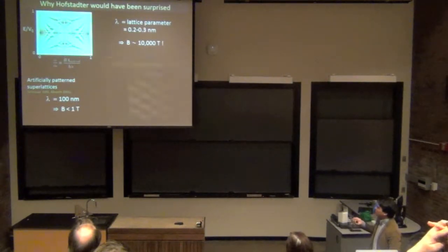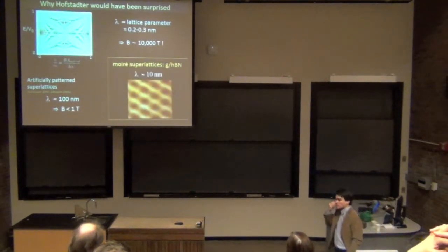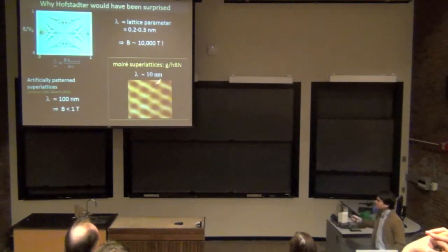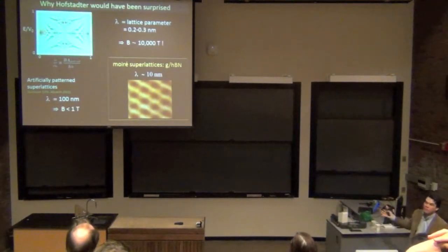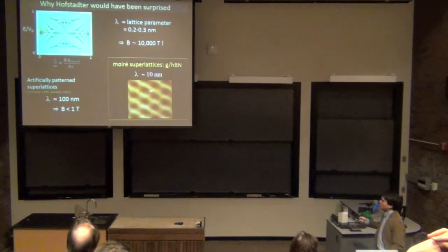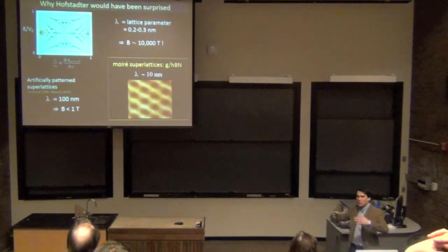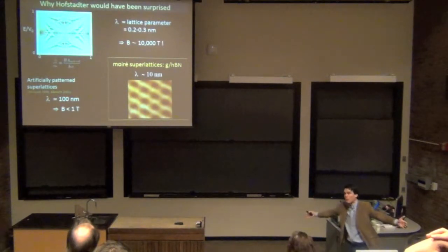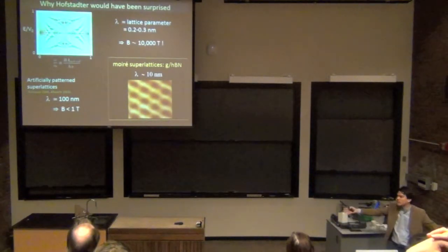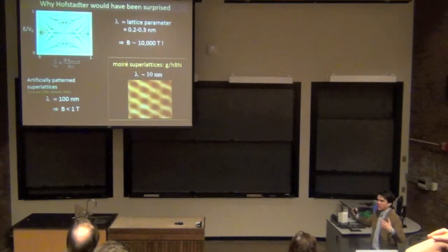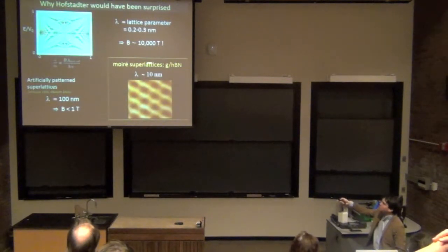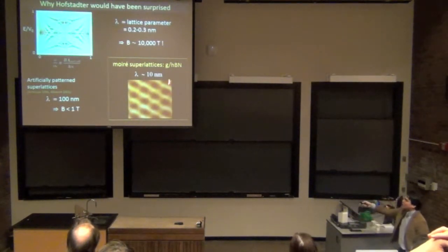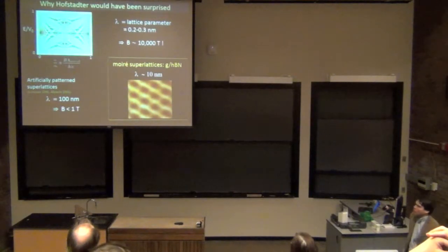So that's where the 10 nanometers comes into play. This 10 nanometer potential acts like a beautiful periodic potential, and not only that, it acts like a beautiful periodic potential on the scale of the whole sample. So we basically have a perfect periodic lattice over the scale of maybe 100 times this lattice constant, or even larger.